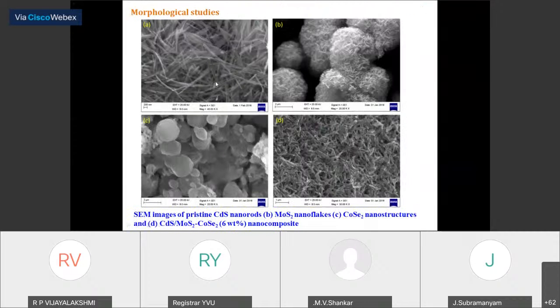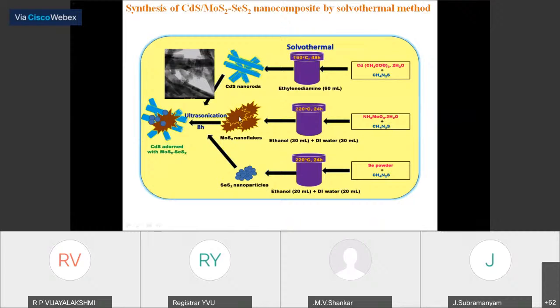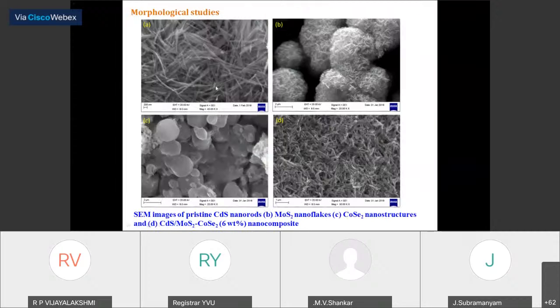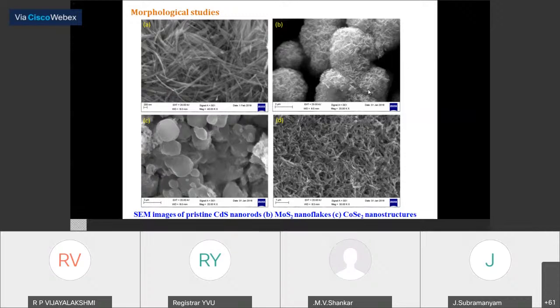So these are some micrographs of the rods, flakes and powders we synthesized by using the solvothermal method. When you observe the morphology of the cadmium sulfide and molybdenum sulfide that were synthesized, this is actually the cadmium sulfide. After synthesizing, we got the nanorods in terms of the cadmium sulfide. So this is the molybdenum sulfide. Molybdenum sulfide is actually in terms of a layer structure. That is the structure we have obtained for the molybdenum sulfide.